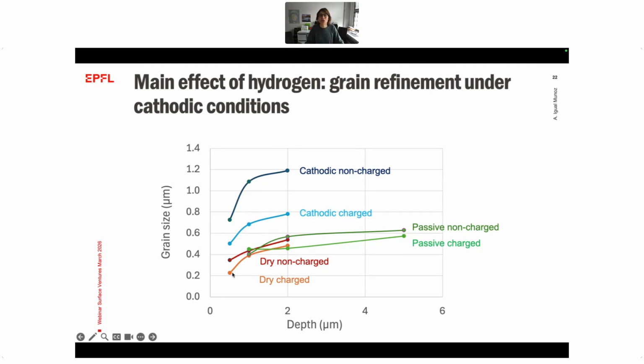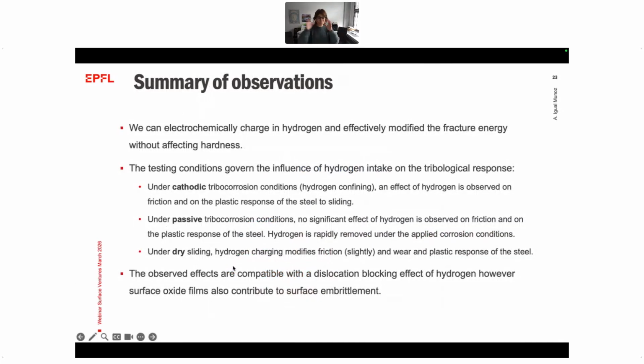Finally, these observations demonstrate that the hydrogen effect is strongly dependent on the electrochemical conditions, in the presence or absence of surface films, even though we may have the same wear mechanism. So, from this point of view, this work allowed us to, first of all, conclude that the electrochemical charging is effective, and we can quantify it through simple measurements such as fracture energy.